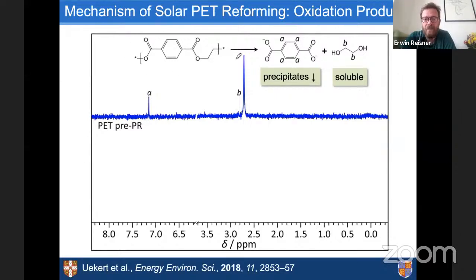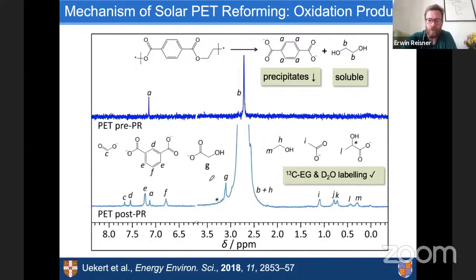So with PET, a copolymer, we break it down into terephthalate plus the ethylene glycol. The terephthalate precipitates under the condition, which means there's a possibility to separate it and recycle it. And then what we're really converting is the ethylene glycol. And then with ethylene glycol, you form this whole range of different products going from formate, glycolate, ethanol, acetate, lactate. And you can also see a little bit of this terephthalate here. This is just an isomer, isophthalate, in fact. And this is only here as a filler. So this is not a new product that has come from isomerization. This has just already been in the PET before.